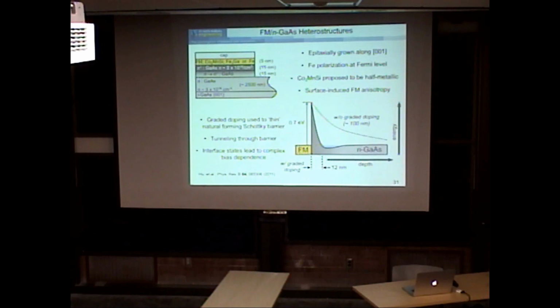The other thing we have to do to be able to get this to work, for the spin injection, is to have a contact. When you put metal down on gallium arsenide, you always get what's called a Schottky barrier. I hope you all know what a Schottky barrier is. Okay? You all know a Schottky barrier. Good. So we get a Schottky barrier, typically with a barrier height of about 0.7 eV. And what we've done is we have to dope the gallium arsenide very heavily just below the contact. So we grow a 5 times 10 to the 18 layer here to make this thin enough to be able to tunnel through. If we don't, we get a very, very large depletion region and you don't get any tunneling.